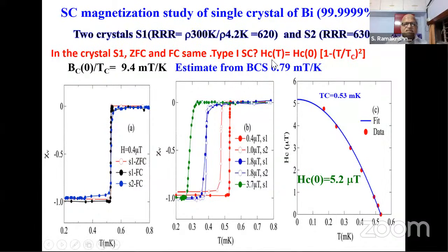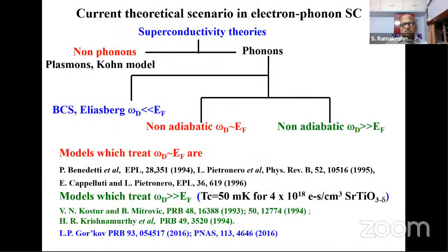The BCS theory tells you that the ratio of the critical field to the temperature should be this, and it is 10 times lower than what we observe. The point is that the BCS theory is not applicable, but we just wanted to see what happens, and the numbers also clearly don't match.